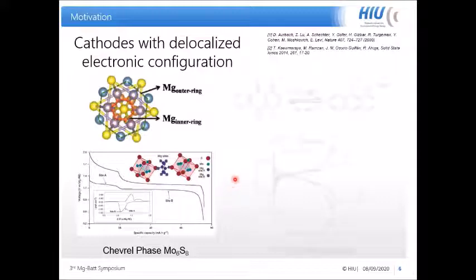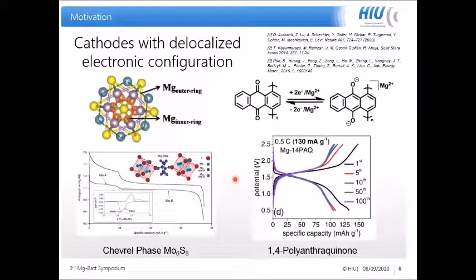What I also want to point out is that with this delocalized electronic configuration, even the strong magnesium-oxygen interaction can be somehow mitigated. An example is the polymer case. Here I show you a polyanthraquinone structure, and basically we have a conjugated structure over the molecular chains. In this case the battery could deliver a very nice plateau with very good cyclic stability. Here I show you up to 100 cycles in the publication.